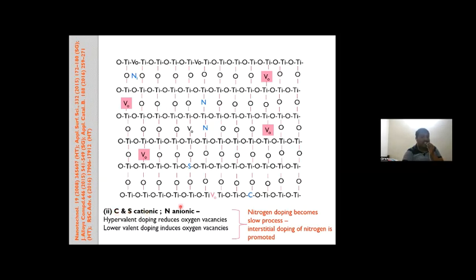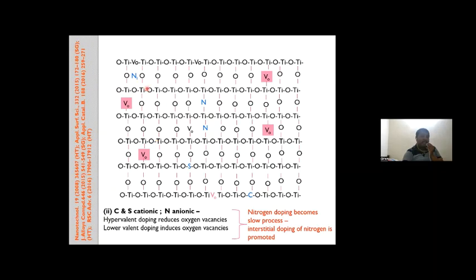Because there is a decrease in oxygen vacancy concentration, nitrogen doping is more slowly absorbed. Without sufficient sites, some nitrogen enters interstitial sites — this is a very good observation. When nitrogen occupies both substitutional and interstitial sites, and sulfur occupies titanium sites, the change in oxygen vacancy structure is responsible for these doping modes. This was observed by hydrothermal and sol-gel methods.